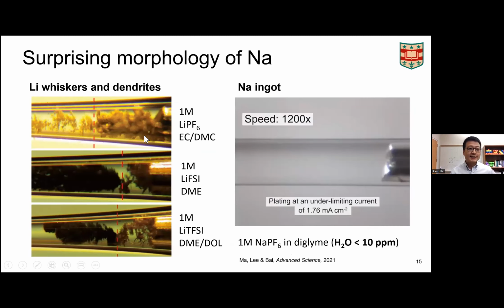And so I showed you that for lithium growth, you will have this transition from a very mossy, very ugly collection of whiskers, then transit to dendrites and fractal structures, fast advancing fractal structures. And this is true for all types of lithium ion battery electrolytes. This means different salt, different solvent. Salt is like sodium chloride, the table salt, right? Solvent, water could be one solvent, but it cannot be used for lithium metal because that will be strong reactions. The liquids we use here are non-aqueous electrolytes that are compatible with the metals.